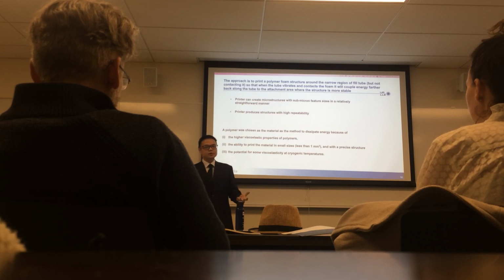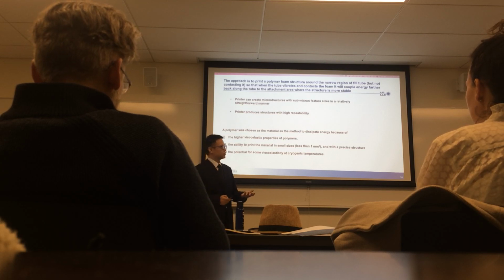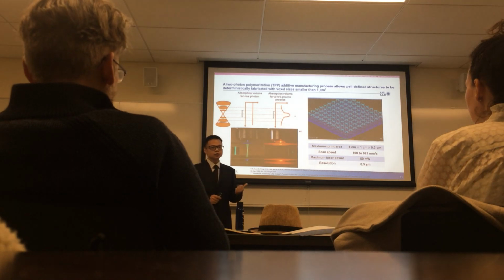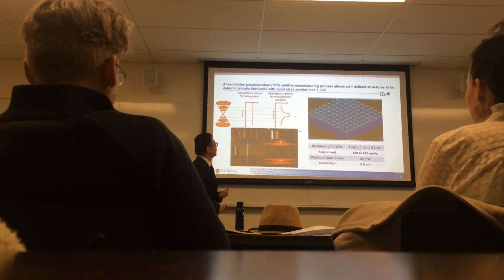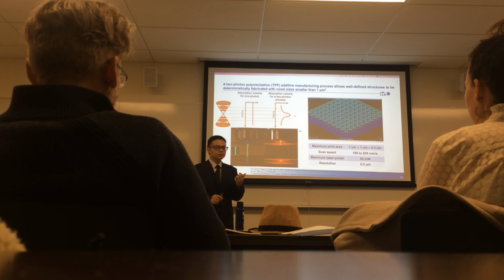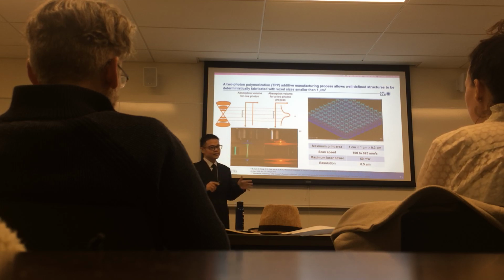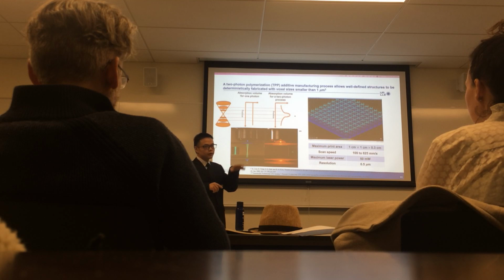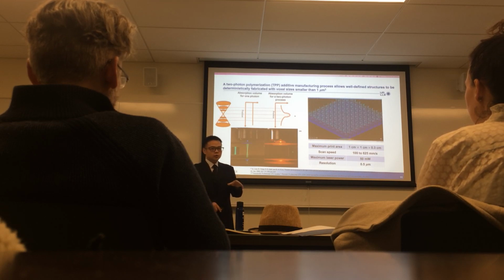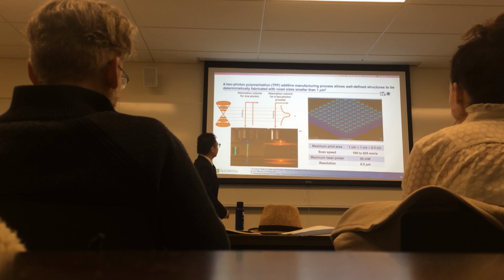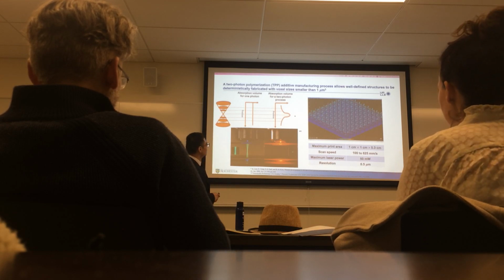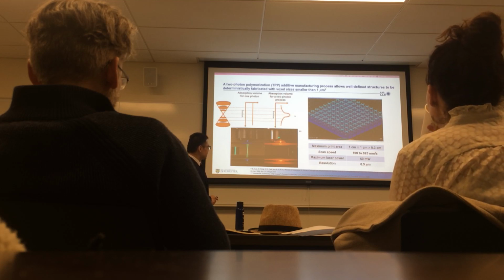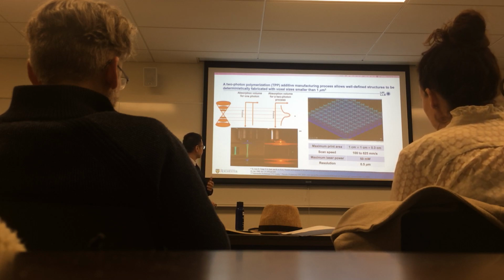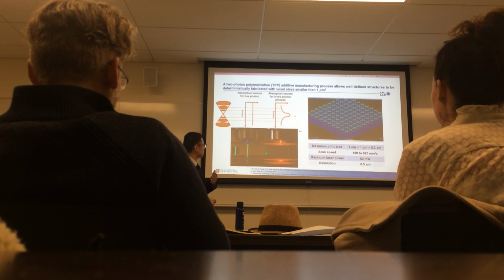Okay, what kind of 3D printer could print out these tiny structures? We use a two-photon polymerization 3D printer. It's like a traditional laser 3D printer that uses a laser to cure liquid resin. At the focus point, the liquid monomer will transform to solid polymer. But the two-photon polymerization 3D printer has a very high resolution compared to the traditional one. That's because it has a smaller focus point.